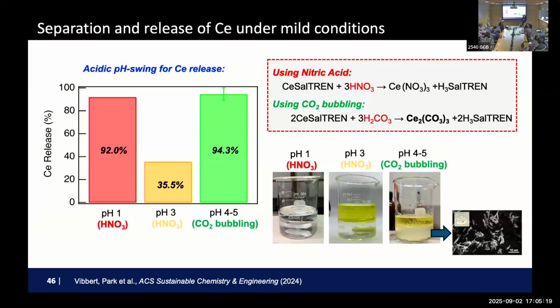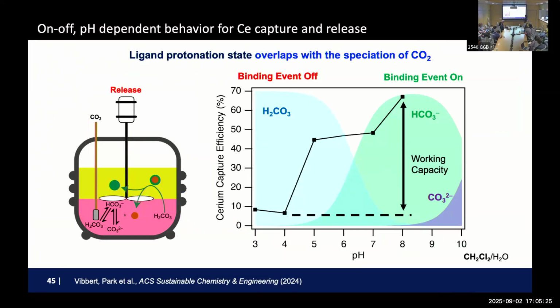Bubbling CO2 back and forth is done before. It's not like that's difficult, but people did not do it because they didn't have a ligand that operates in this window. So if you look at the binding on and off, a lot of these liquid extraction ligands, they bind here, but they won't release until pH 1. That's why we can use it. So we were looking for a structural ligand which opens up just a little bit at the minimum pH. That's what we are looking for. So it's not the most effective one, but a greener one.